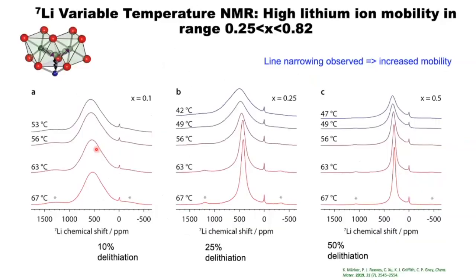That mystery was explained by Katerina's studies, where she simply took the materials and heated them up. When you look at a material that's barely delithiated, you see very little change in the spectrum as you change the temperature. In contrast, if you move to 0.25 and you heat the material up, you see this dramatic narrowing of the lines, and that's indicative of increased mobility. So the lithium ions are hopping between the different sites that give you this broad distribution, so that you only see the average shift coming from all the average environments.